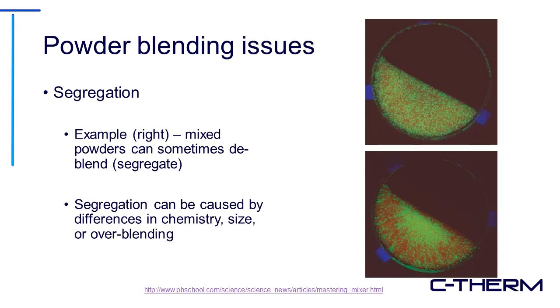So there's a couple powder blending issues that are pretty common and have quality control implications in terms of the final product. So one of the most common ones is segregation. So if you have a well-mixed powder here and then you overblend it, sometimes you can get segregation or what's sometimes called deblending of the powder. And the segregation can be caused by a variety of factors, including particle size, density, and material chemistry. But even for unstable blends that will eventually segregate, you can usually find a shorter blend time or sometimes a longer blend time that will let you avoid the segregation.